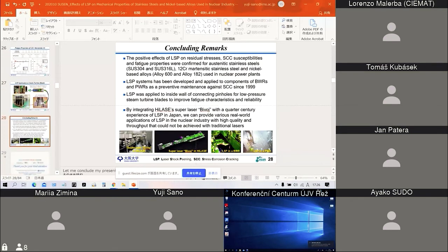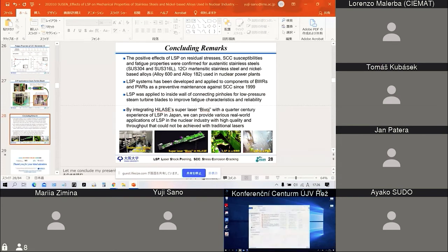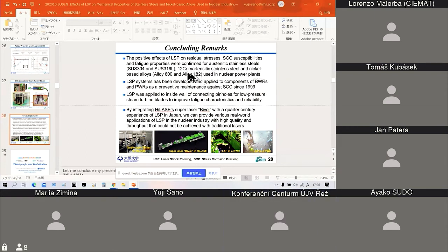So let me conclude my presentation with this viewgraph. The positive effect of LSP on residual stresses, stress corrosion cracking susceptibility, and fatigue properties were confirmed for stainless steels, 12 chrome steel, and nickel-based alloy. And the LSP system has been developed and applied to components of BWRs and PWRs as a preventive maintenance against stress corrosion cracking since 1999.